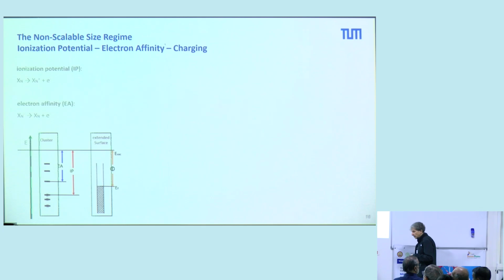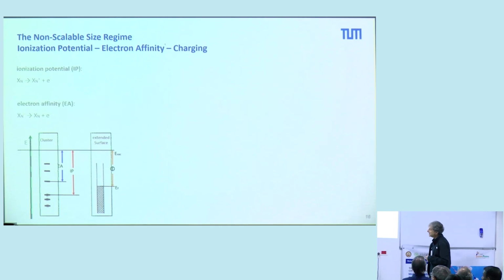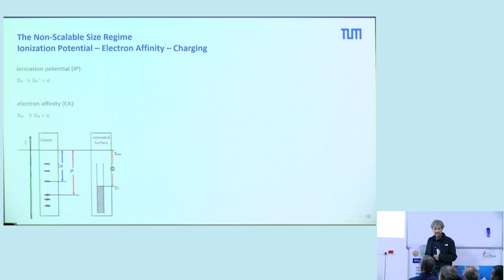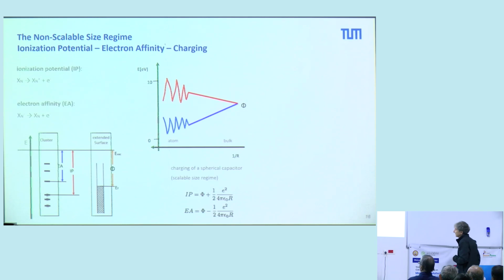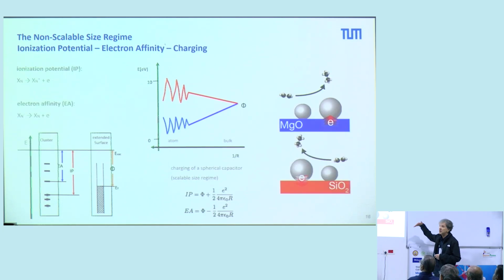But there are other important facts in this non-scalable size regime. As I mentioned before, we have a HOMO-LUMO gap. We have different ionization potentials and electron affinities, very different from the bulk. And this is, of course, important for catalysis because often these particles are on a support material and you can have a charge transfer to the cluster or from the cluster to the bulk. That means you change the electronic structure. If you have a bulk particle, it doesn't matter if you add a single charge. But here, on these very small clusters, you change the electronic structure. That means you can tune the catalytic properties not only by size, but also by the interaction with the support.